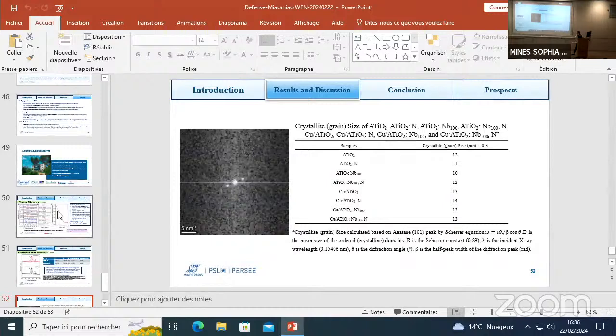So you mentioned, in fact, it could be due to aggregation, and we can see in TEM an aggregate and not a single particle. But it could also be due to core-shell particles with a crystalline core and an amorphous shell.